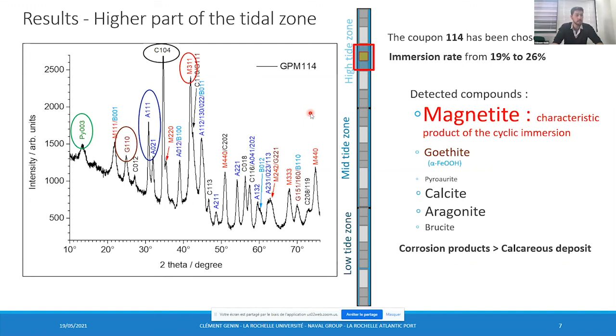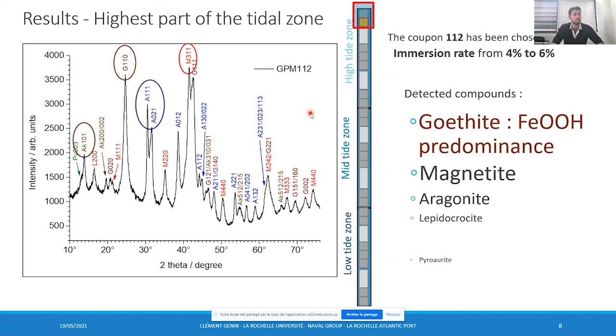I mean that corrosion products are more present, are predominant above calcareous deposit, which led to the hypothesis that cathodic protection may not be efficient in this zone. This is a transition zone between this slide and the previous one. The highest part of the tidal zone is here, representative of this part, which sees really few immersion rate from 4 to 6%. And there, goethite is a predominant corrosion product, which is an oxo hydroxide, which indicates again a huge flow of dioxygen.